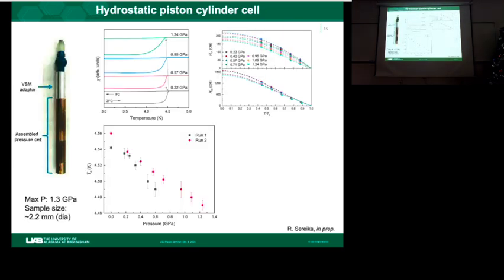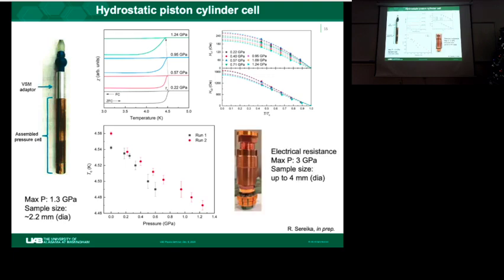As I mentioned in the second slide, this is a hydrostatic piston cylinder cell that you can put in the PPMS VSM coil. If you have a large bore coil, you can actually measure magnetization up to 1.3 GPa. And in this case, the sample size is very decent compared to the sample size in the diamond anvil cell, so you can study superconductivity pretty easily. This is an example of palladium telluride under high pressure. And this is another type of piston cylinder cell where we can put oil pressure medium in there and seal it, and also achieve a hydrostatic pressure medium up to 3 GPa.